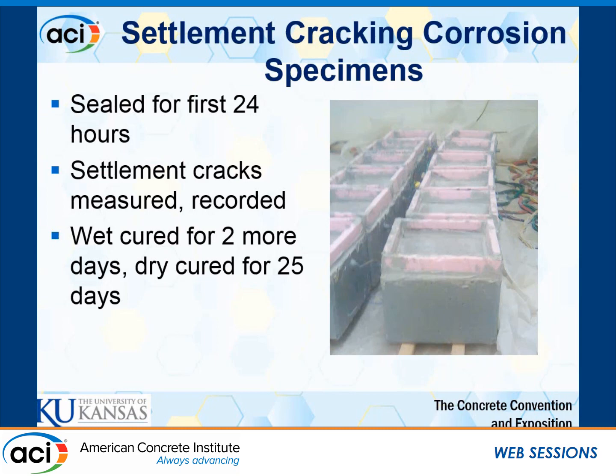And for our corrosion testing, we wet cure for another 2 days. And for a total of 28 days after casting, that's when everything is connected across a 10 ohm resistor, the switch is turned on, and the specimens are ponded with our salt solution to begin corrosion testing.